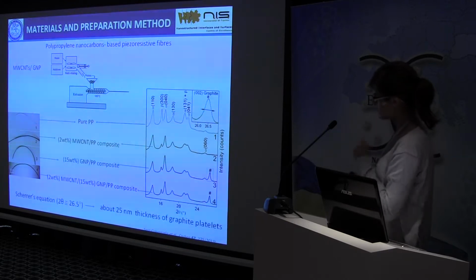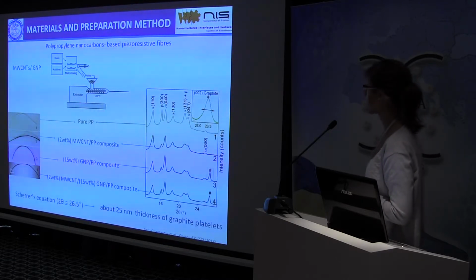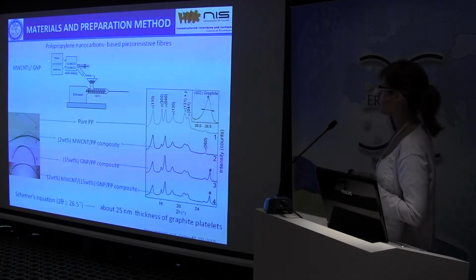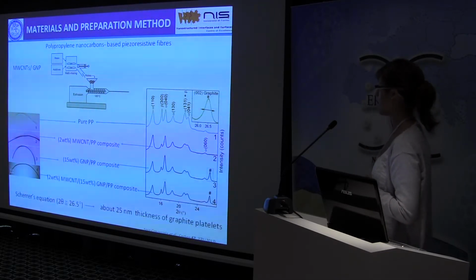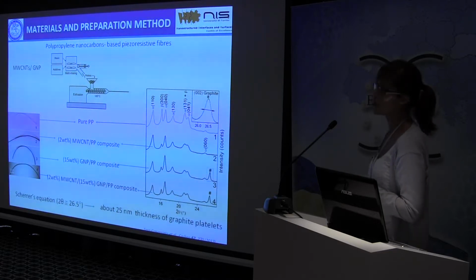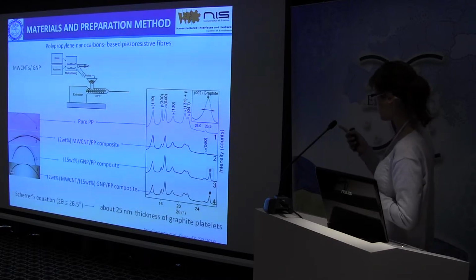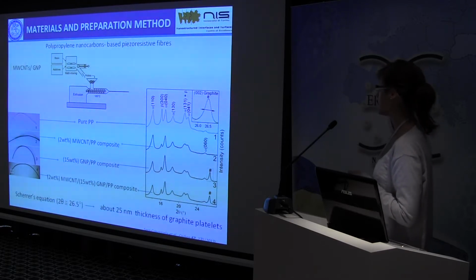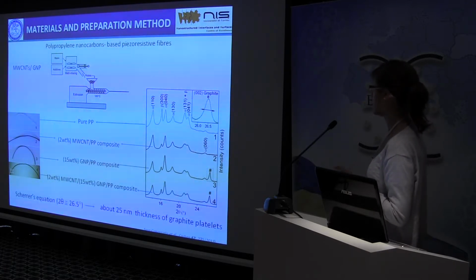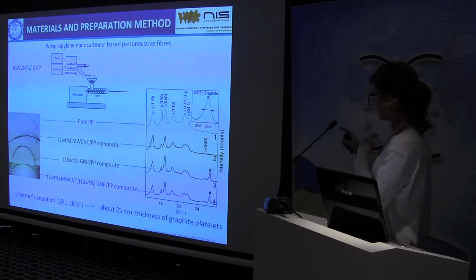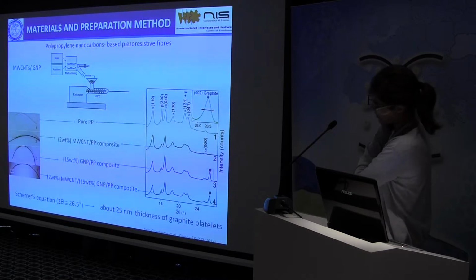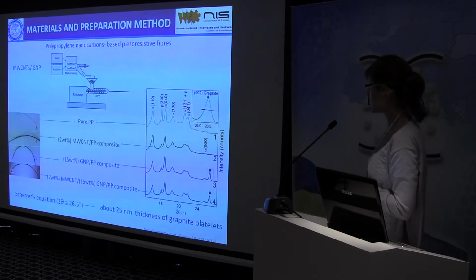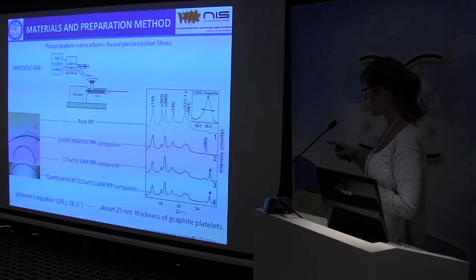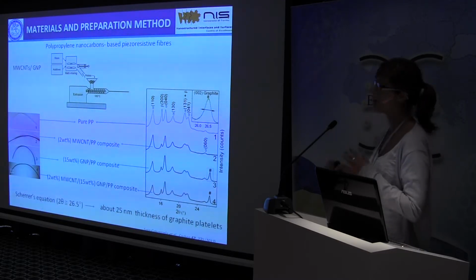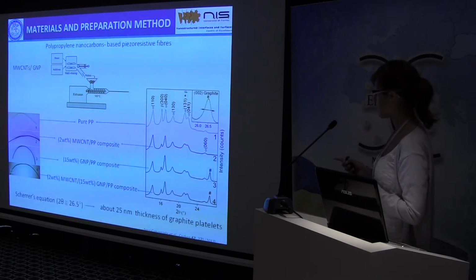The first pattern is about the pure polypropylene fiber. Here you can see that there are narrow peaks which emerge from a very broad feature, which refers to the amorphous phase of the polypropylene. And these peaks reveal the presence of two phases of the polypropylene, the alpha and the beta phases. Then the third pattern refers to the composite containing only graphite nanoplatelets, and the fourth one refers to the fiber containing both nanofillers, multi-wall carbon nanotubes and graphite nanoplatelets.